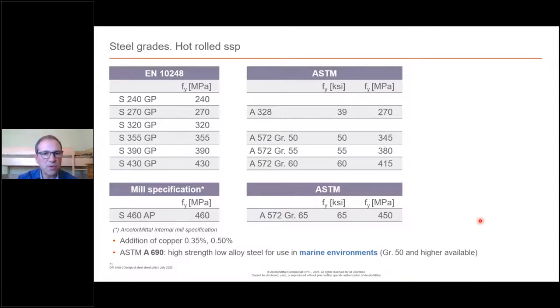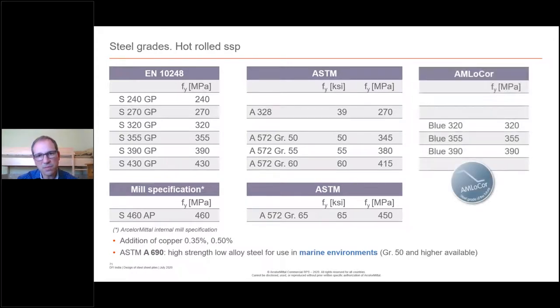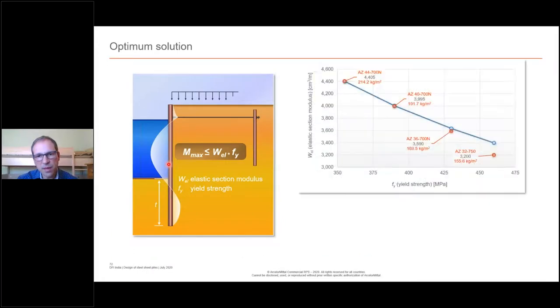So we can supply according to the European standard, which is EN 10248. We can also supply according to ASTM. Nowadays, S355GP would be the standard steel grade, but as we'll see, using a higher steel grade will actually reduce the amount of steel that you need. So even though you have to pay maybe a little bit more because of the alloys that the manufacturer has to put into the steel grade to achieve this yield strength, the solution will be cheaper. And then we have AMLoCor, but I will come back to that later.